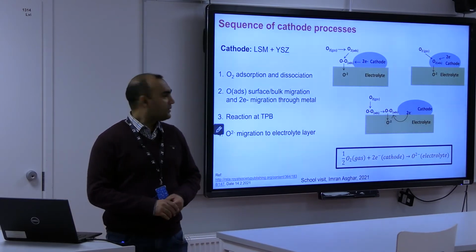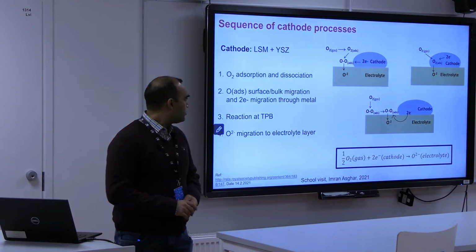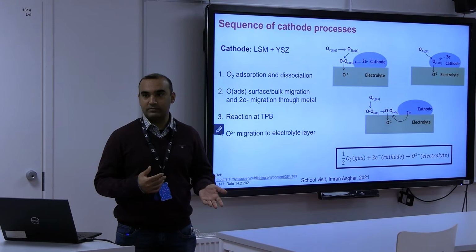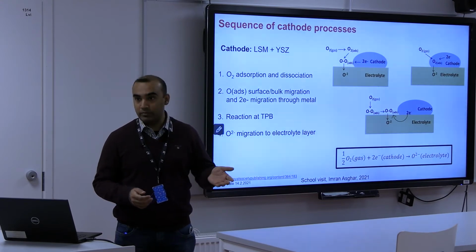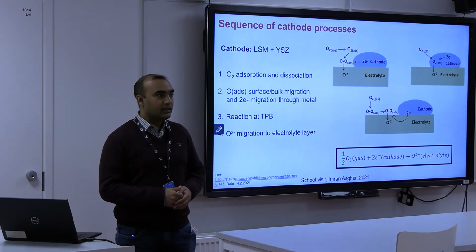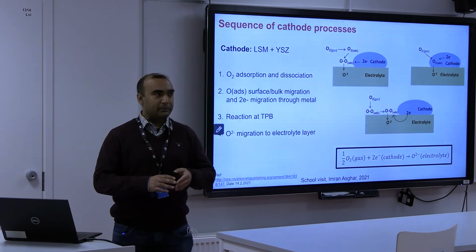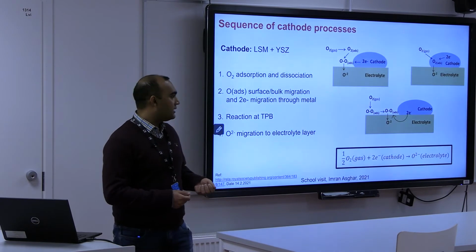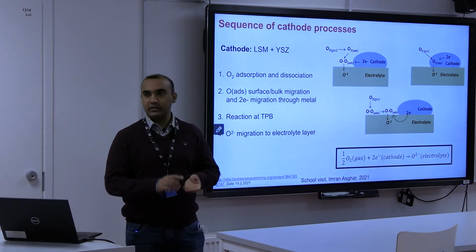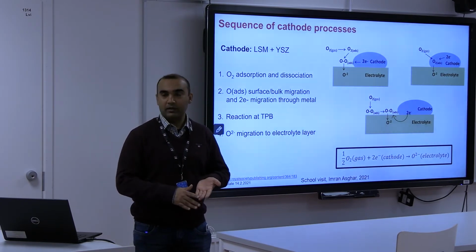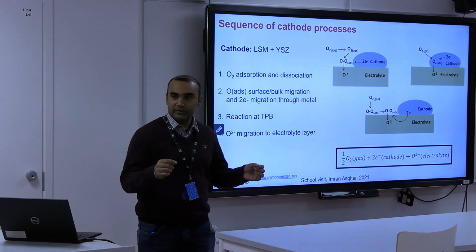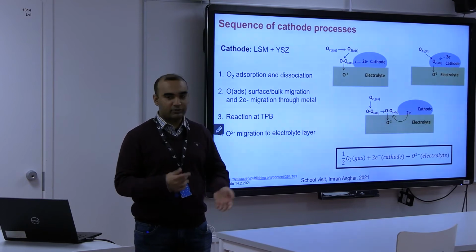Yeah, these cells are not so thick. These electrode layers, from a functional point of view, can be only a few microns, like 1 micron to 10 micrometers is sufficient for the process. But the thing is, if the cells are so thin, then mechanically they are not so stable. So usually what we do is make one of those 3 layers thicker, let's say about 300 micrometers, and the other layers are a few micrometers. So mostly there are different structural configurations.